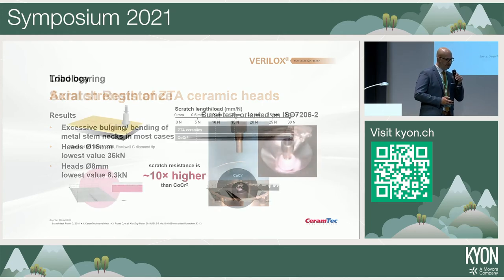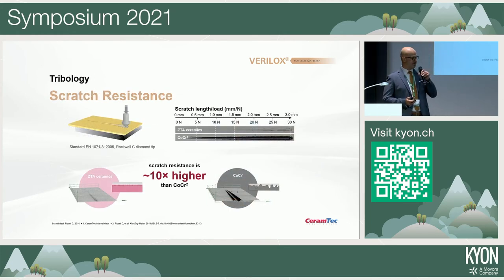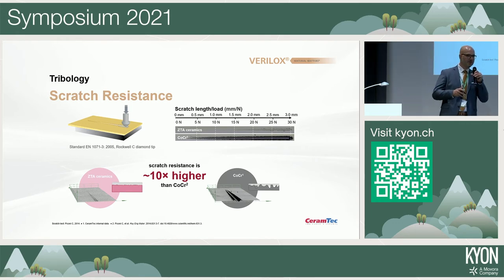A second test that I want to show you here is the scratch resistance. And that is important if you want to use ceramic for articulation surfaces. Scratch resistance is tested by using a diamond tip, putting it on top of a surface, then move it over the surface and increase the axial force that acts onto this diamond tip. And the aim is to provoke a scratch in the surface.